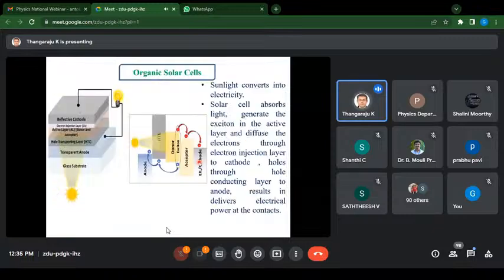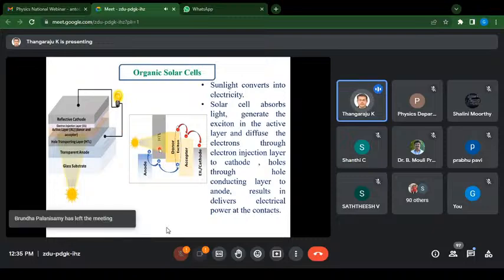And our group is also working on organic solar cells. You can see that organic materials are being used in solar cells. In the case of organic solar cells, there would be donor and acceptor molecules. When the sunlight falls on the donor molecule, it will excite the electrons, and the electron hole pair, that is the exciton, would be generated. These excitons would be dissociated at the interface. You can see that the electron hole pair, the exciton, will diffuse to the interface in the donor layer. When it reaches the interface, there would be a large energy barrier for the holes, and there is no energy barrier for the electrons, so the exciton gets dissociated.